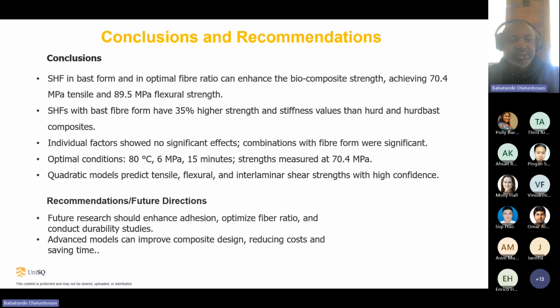Using RSM to optimize the conditions, the optimal condition given is a molding temperature of 80 degrees, about 6 megapascal pressure, for 15 minutes, which actually gave the best strength of 70.4 megapascal. The quadratic models that were developed can predict the mechanical properties with high confidence. We could see from the R-squared values a high confidence of about 92%, 93%, and 83% respectively for tensile, flexural, and interlaminar shear.